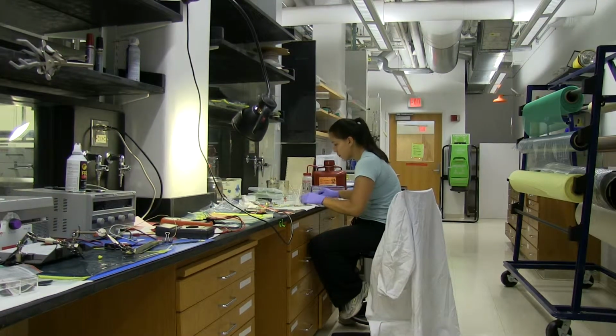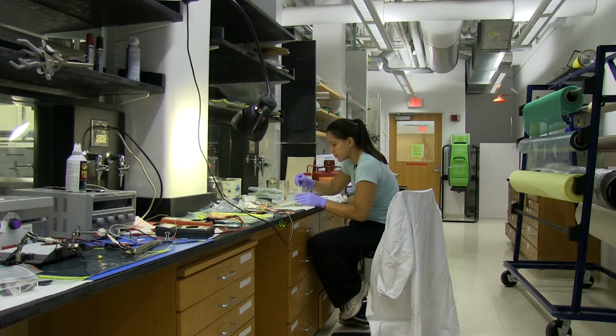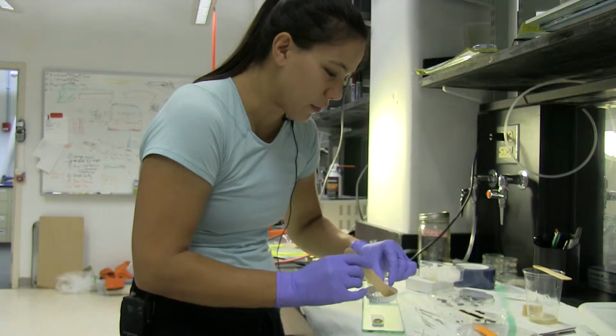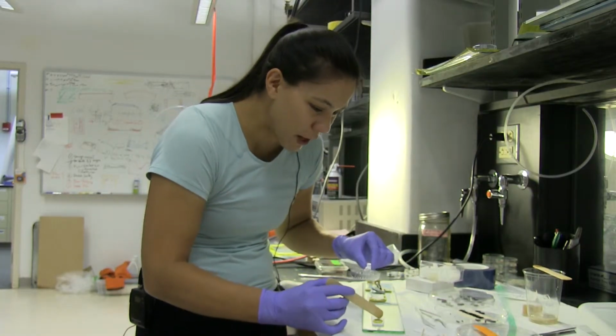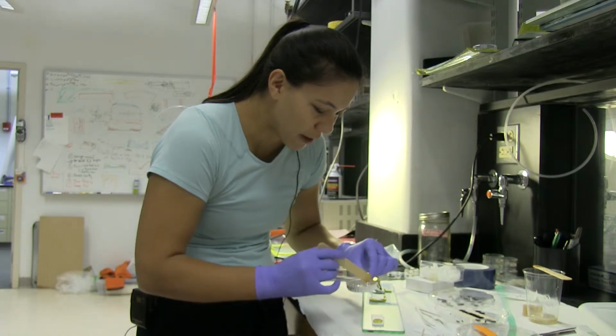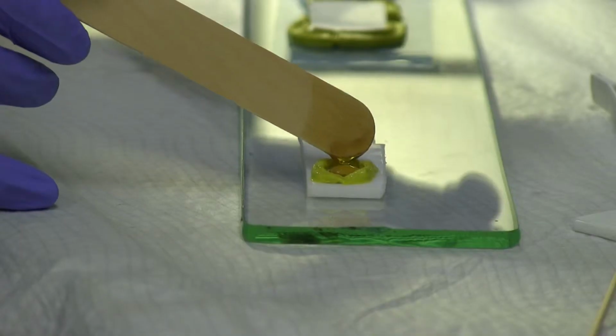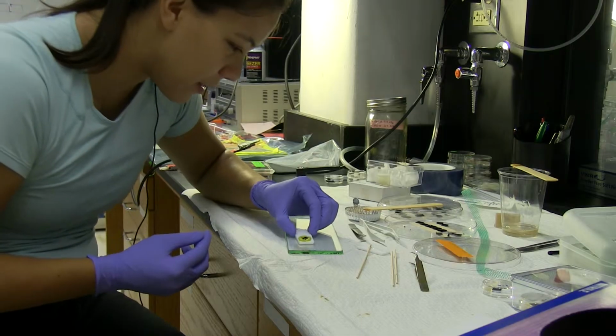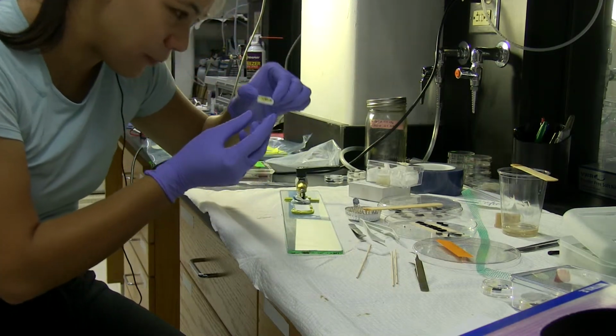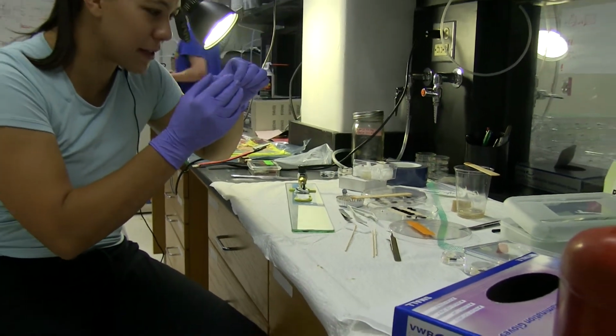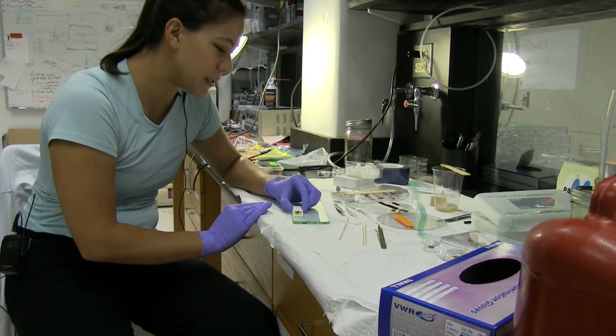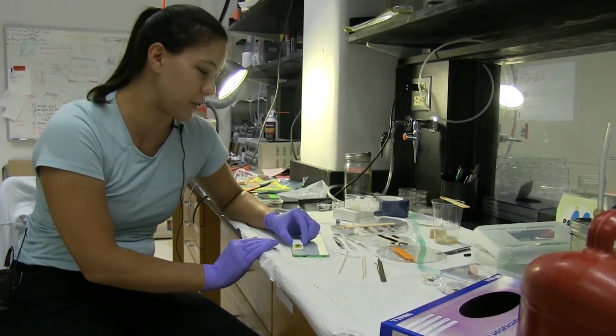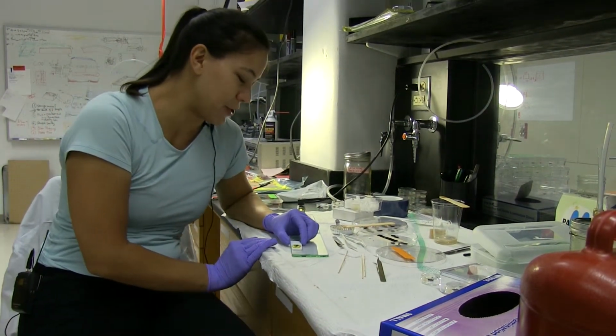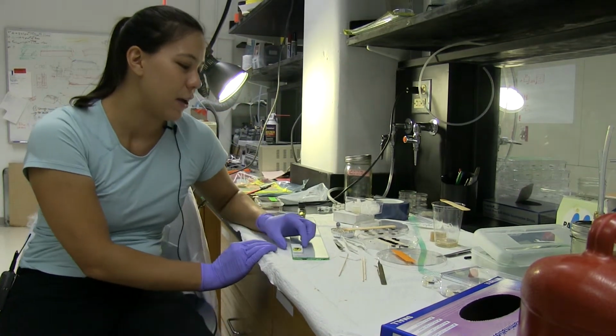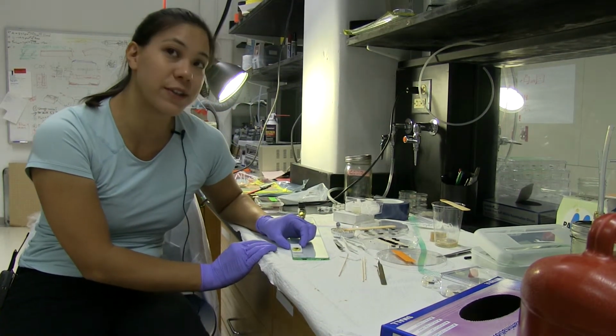Next kind of epoxy that I'll be using is one designed for aerospace. I'm going to put a few drops into my little pool that I've made in this trial. These fibers are now half submerged inside the bubble of epoxy. These guys I'm going to put into the oven afterwards to cure. They don't cure at room temperature, so I have to put them in the oven at 160 Celsius for 2 hours for them to cure.